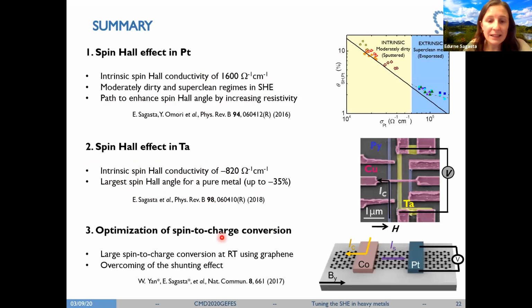And in the last part, I have shown you a novel device where we have combined graphene and platinum, because in this system we are able to overcome the shunting effect and obtain very large spin to charge current conversions at room temperature.